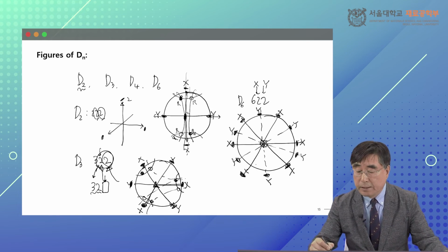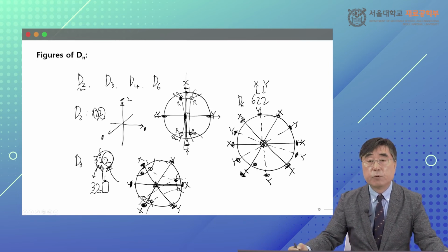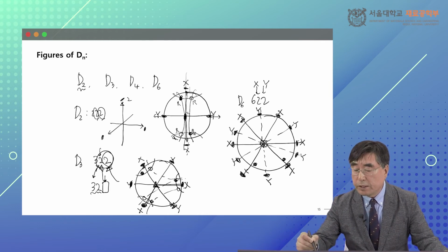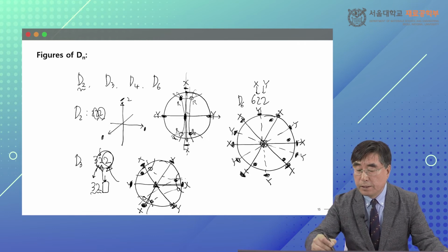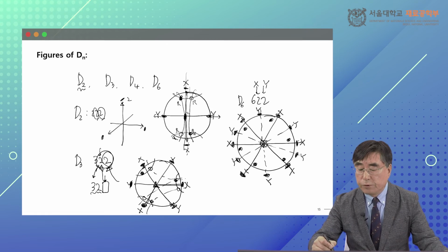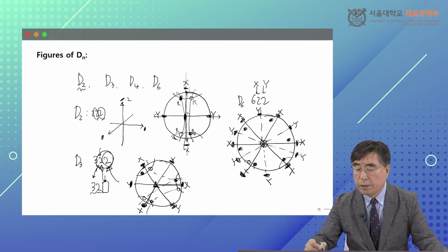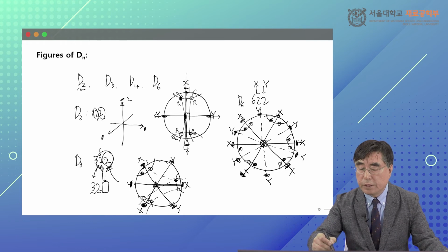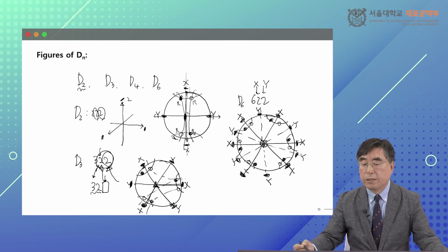Okay, symmetry-wise, you have 6-fold. If I put one general pole, upper right hand, then 6-fold generates 6, and 6 in here, 6 in here, 6 in here, and 6 in here. Now, if I do the y-x operation, 2-fold, the down pole generates here, and here, and here, and here, and here, and here. So the multiplication factor is 12.